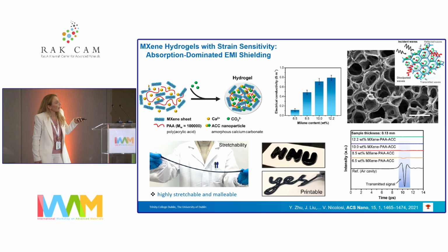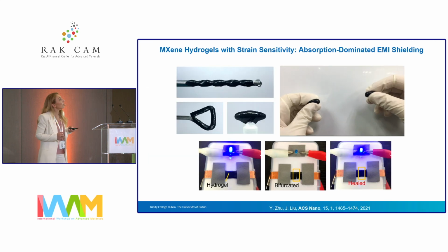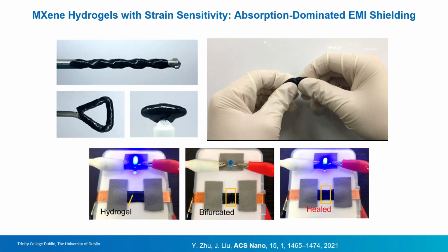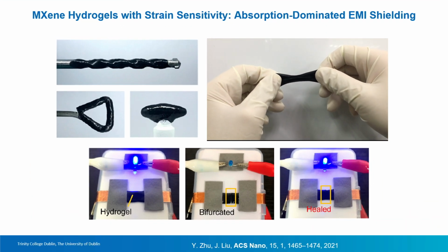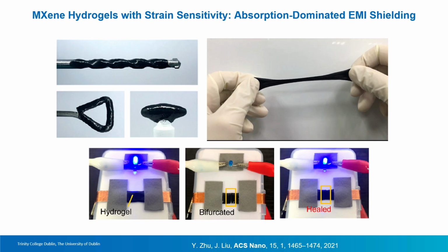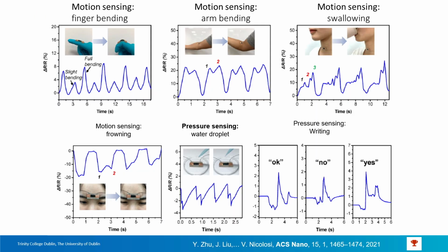Here you see an identical film without MXenes. You see the terahertz domain type of spectrum, and only by adding 6.5% of MXenes, you already have a sort of 99% screening of this emission. The nice thing also comes from the fact that these type of hydrogels are very printable and completely stretchable and healable. So they can adhere to pretty much any surface, and they are self-healable as well, which means that you can recombine them, and of course they retain their electrical conductivity.